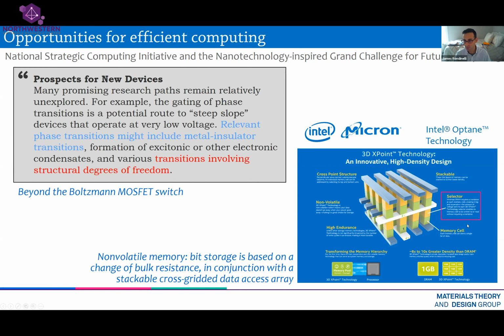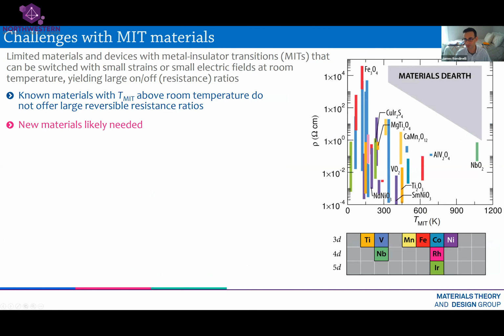And so what we're looking for in this specific example is improved selector materials. And the fundamental aspect of the selector material is that it undergoes a metal insulator transition, okay? And what that means is that when I transition from the metallic state to the electrically insulating state, there should be a large change in the resistivity. And that's what this large on-off resistivity ratio is. And what I'm plotting for you in the upper right-hand corner of this slide is resistivity as a function of temperature for a number of materials.